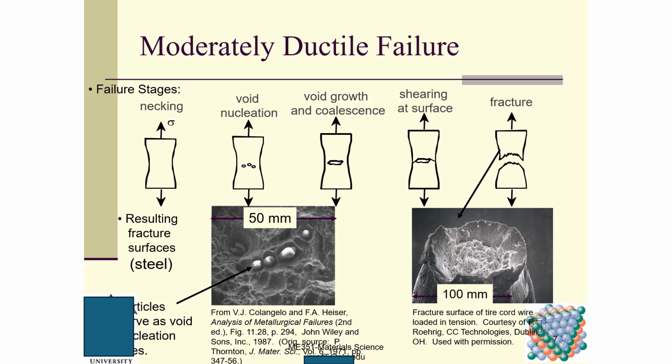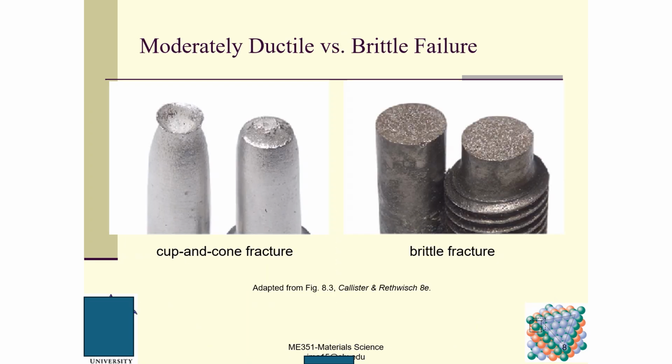This surface forms an angle with this axis of almost 45 degrees. Theoretically it should be 45 degrees, but because there are a lot of impurities in the material, experimentally the angle is kind of off from 45 degrees, but it is understandable. Any questions regarding this slide? No questions? We move on to the next slide.